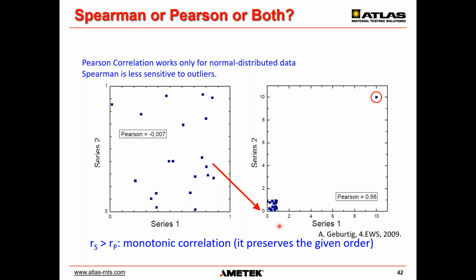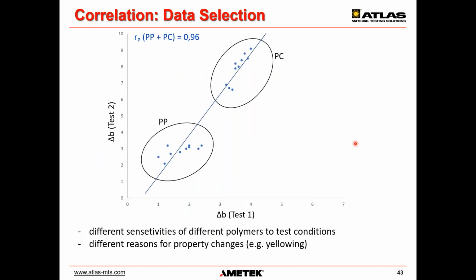And then typically something's wrong, or something's off, and something has to be considered if the Pearson correlation coefficient is bigger compared to the Spearman correlation coefficient. In this example, we have on the right side a perfect correlation, on the left side statistical data, and actually the right side is the same data with one outlier, which makes it a linear correlation, but it's not a real linear correlation. It's only linear because of the outlier.